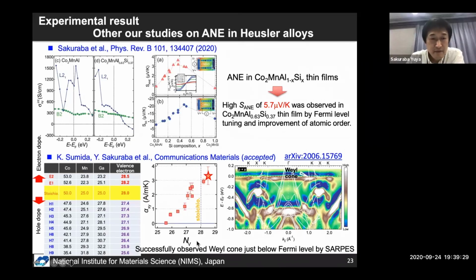Yeah. So actually, we calculated this in the paper. Sorry, today I don't have the viewgraph, but in this paper, we show the sigma xy for the L21 and B2 disordered cases. And we show the value of alpha xy at around the Fermi level. As you can see, alpha xy is largely reduced by B2 disordering. So we saw this kind of data. I see.